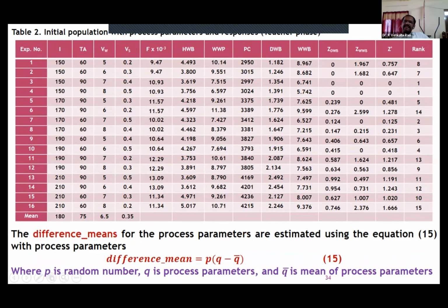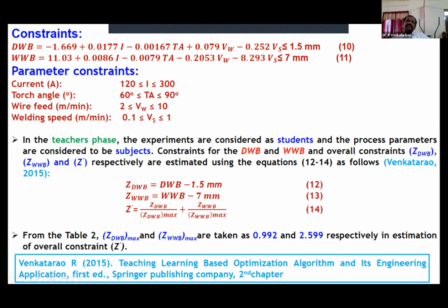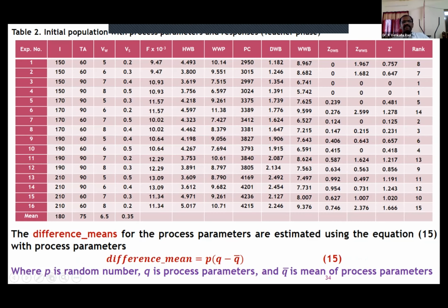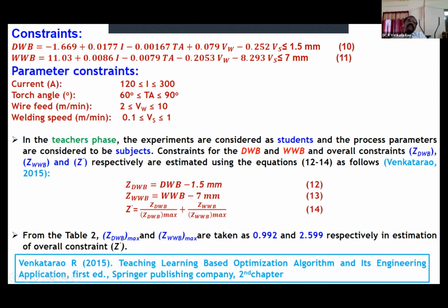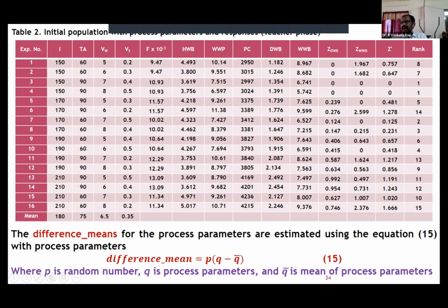Similarly, the overall constraint was estimated using equations 12 to 14 for all 16 experiments based on the constraints. They should be 0 because here we have taken a minimization problem. These values should be as low as possible, so experiments with low constraint values are given better ranks, and the remaining ones are given the remaining ranks. Like that, ranks are assigned to all the experiments.